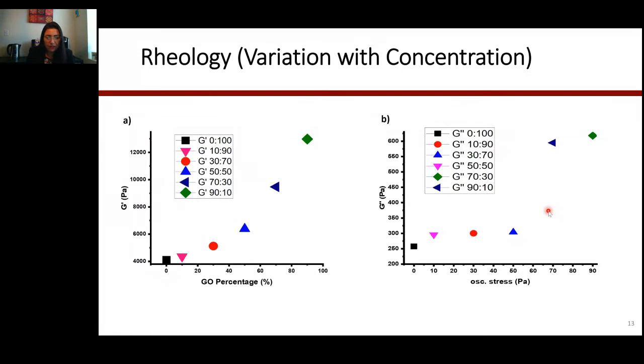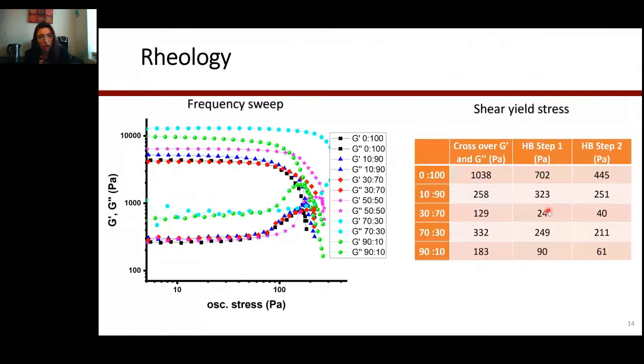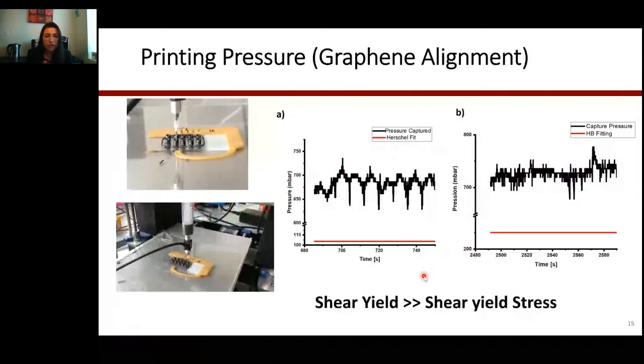Why am I talking about the rheology? Because there were two different ways to figure out the alignment of the printing. We could look at the crossover point between G prime and G double prime, or the Herschel-Bulkley model. Doing those two methods, we had to ensure that the pressure we were printing at was above the shear yield stress.